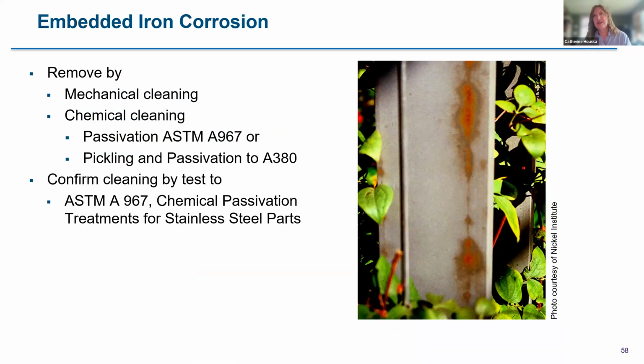If you get embedded iron on a surface, then there are a couple ASTM standards for removal of that iron. If it's superficial, then A967 would be sufficient. If it's deeply embedded, as it is in this image, then you need to probably grind and pickle.